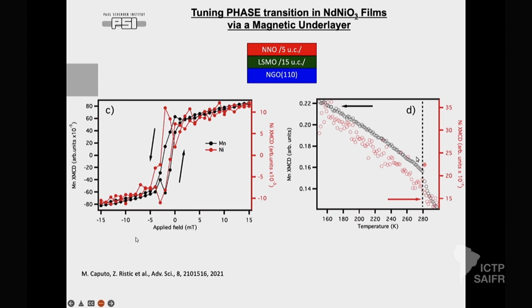If you are looking at this set of data, the XMCD data in this bilayer, LSMO, so in manganese, shows the transition at 280. When it is just LSMO with the same thickness grown on NGO, this TC is about 320, 340. So there is kind of an exchange bias on the LSMO side as well. And as you have been suggesting, it will also be important to go into details to see what happened on the LSMO side as well.